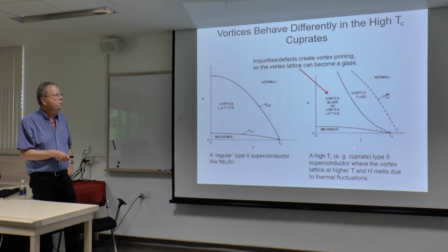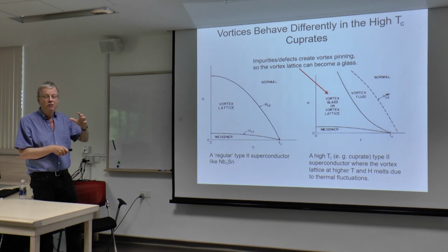So in a high TC cuprate, there's this mean field upper critical field here. Below that, because of thermal fluctuations, which I'm not a big expert on, but which is very important in the cuprates, it's not a frozen thing, it's a vortex fluid, so the vortices move around. This means that when you put a current through it, there's losses. F equals V cross B. F times distance equals work. There's losses. If the vortices can move in the fluid, you get losses. So this is not where you want to run your high temperature superconducting cuprate magnet, because you'll be pumping energy in for the rest of its life at those fields.